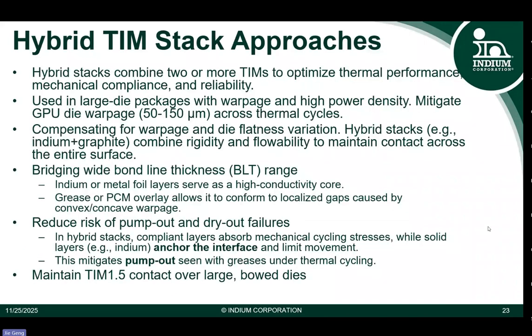Then I'll talk about the hybrid TIM stacking approaches. Because of the warpage challenge, sometimes only one material cannot meet the thermal performance, the mechanical compliance, and also the reliability. So in that case, we have to think about how to combine two or more TIMs together to achieve that goal. An example of the stacking is putting indium foil and a graphite sheet together. So in that case, you have the advantages from two different materials. So combine the rigidity and the flowability to maintain contact across the whole surface.